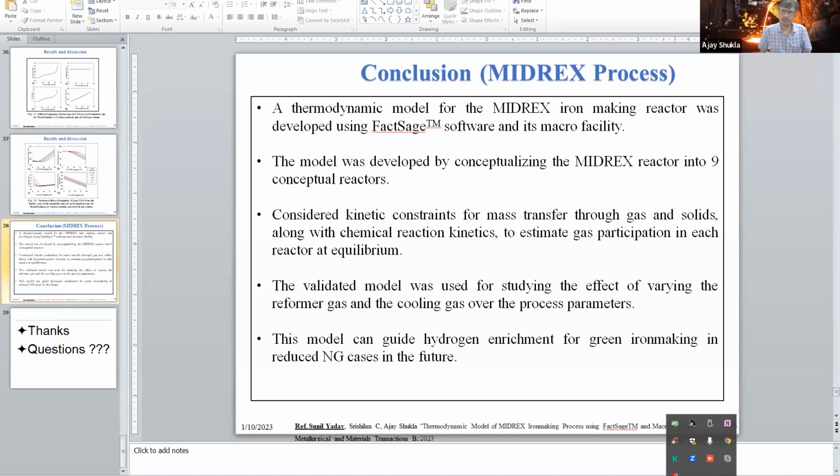Sir, I agree. Thanks for asking the question. I agree with your point that metallurgical reactors are not in equilibrium, and they are far away from equilibrium. That is why this approach has been adopted, where I am not saying that the entire reactor is in equilibrium, but that localized regions may be in equilibrium. For example, at the interfaces where two phases meet, they may be in equilibrium because the kinetics is very fast at high temperature.